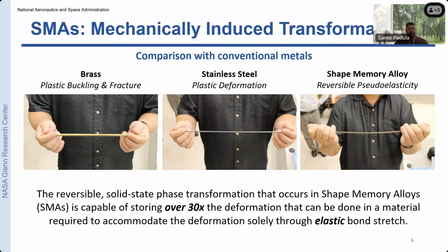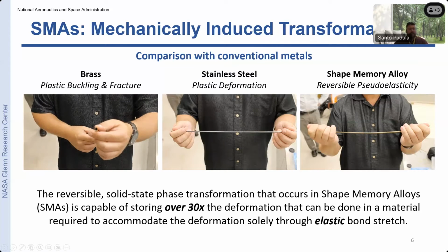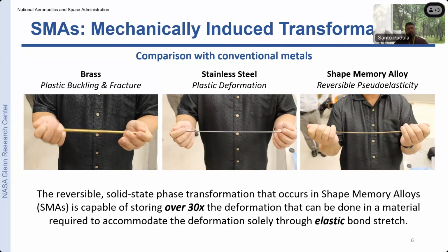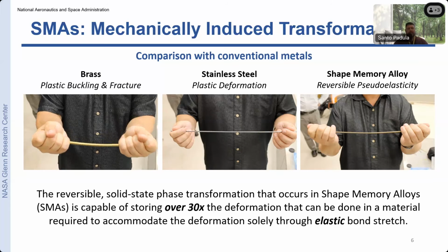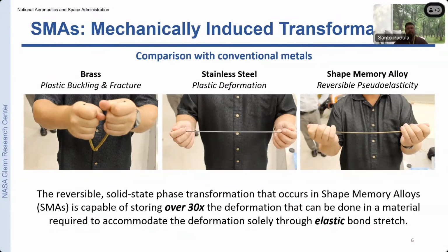In this particular case, we're looking at the mechanically induced transformation. And in these three videos, you're going to see a comparison between the bending deformation of a tube made from brass, stainless steel, and a shape memory alloy, and the reversible potentials in each. So on the left, as we try to take a tube of brass and put bending loads on that tube, we get very little elastic deformation before we immediately go into plastic buckling of the tube wall.